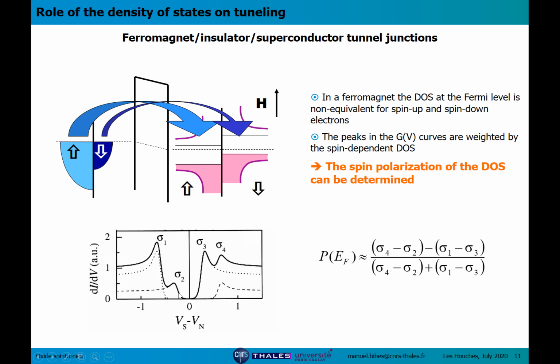Okay? And by fitting, or even simply by measuring the relative heights of these peaks, you are going to be able to determine the relative imbalance of spin up with respect to spin down in the density of state of the ferromagnet. And this is called the spin polarization. So spin polarization is the relative difference between the density of state at spin up and spin down at the Fermi level in the ferromagnet. So these tunneling experiments using the so-called Meservey-Tedrow method were, I think, the first transport method to determine spin polarization. And talking about spintronics, this is very important because spin polarization is probably the key quantity governing the amplitude of spintronics effects.